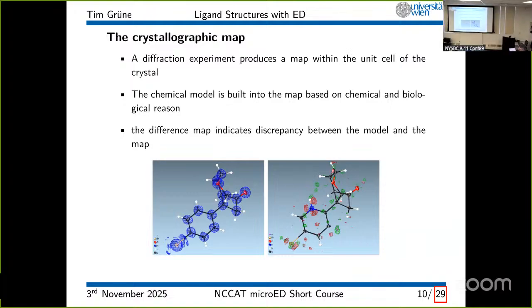Number 10, yes. At the end, you indicated that the data actually was better than the model used for the refinement. You see some effect in the image on the right, the lower left. So can you elaborate on that? So for example, how good the data has to be to see this effect? And what was the problem with the refinement model? So the first question is, how good do my data have to be in order to see an effect if I model it wrongly? And the second part, I didn't understand it. What was the problem with the refinement model? You see the data was better than the refinement model. So what was the limitation of the refinement model?